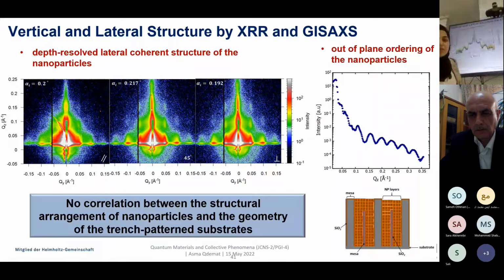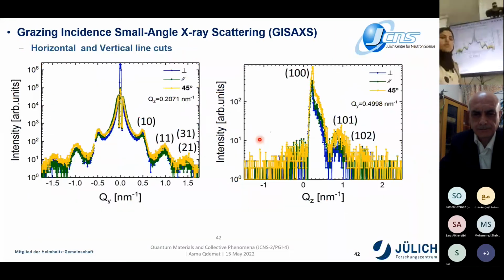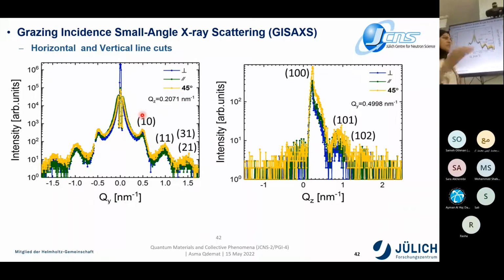Now, to understand this better, we did a horizontal line cut and a vertical line cut. From the horizontal line cut, we can see all the peaks have the same position in the 3 different geometries, and we indexed the particles according to a 2D hexagonal lattice. That means our nanoparticles are arranged into a 2D hexagonal lattice in a plane, and out of plane they are ordered into an FCC structure, a stacking of hexagonal lattices oriented along one direction.